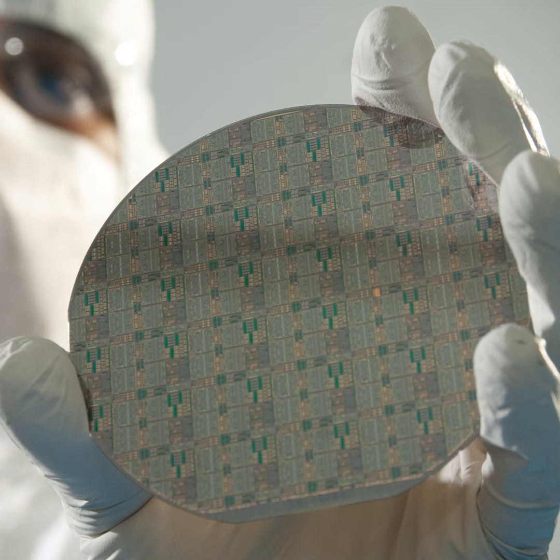One unique aspect of diamond is typically the higher the temperature growth, the better the conductivity. But as you get higher, you start to damage your device. So we want to incorporate a lower temperature diamond growth that the device will still utilize for conductivity, but is still consistent with the processes that are needed to create that transistor.